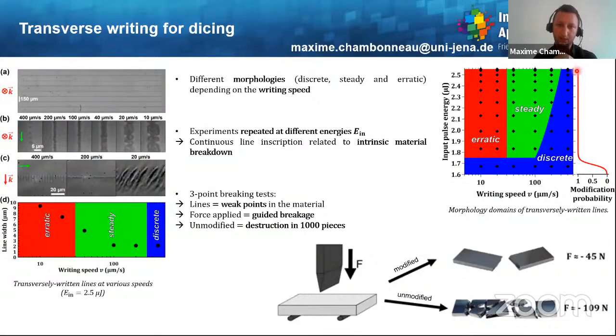And then my colleague Markus Blote has recently carried out some 3-point breaking tests. The idea here is to inscribe lines transversely inside wafers and then apply a pressure to the wafer. As illustrated on this figure at the bottom, the transversely written lines can act as weak points inside the material. And when a force is applied, the cleaving of the wafer is guided.